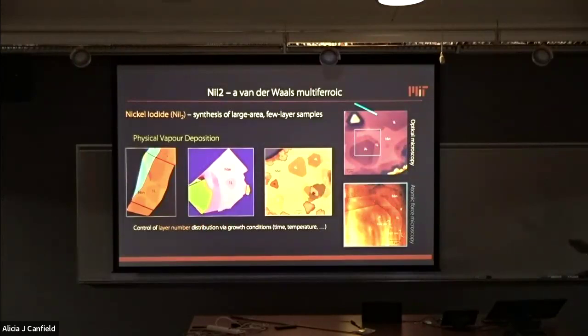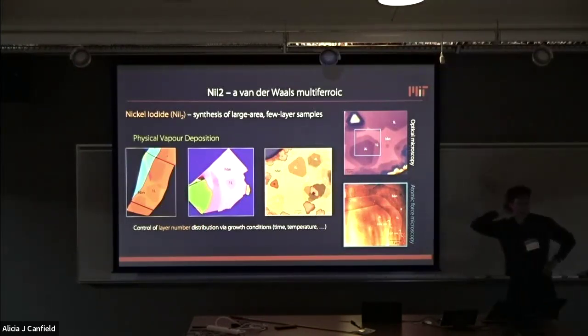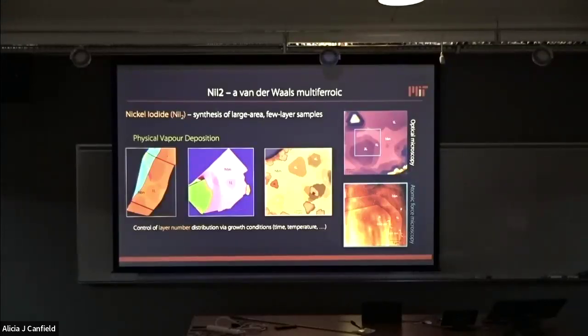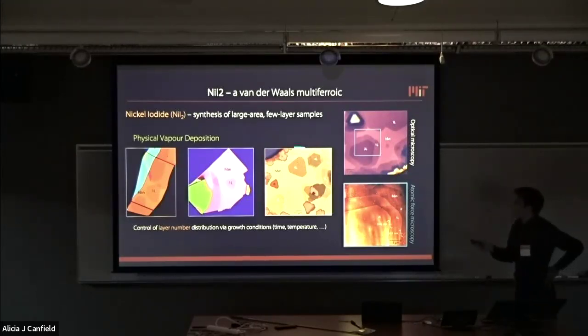So we went ahead and made the samples. These are some thin flakes that are grown in-house using physical vapor deposition in our lab. By tuning the growth conditions, we can go from samples that are mostly single layer to samples that have a distribution of different thicknesses, from 1 layer, 2 layer, 3 layer, which is great for the experiment that we do, because in the ultra-thin limit, we use optical probes to study the properties of the magnetic ground state. And having several samples at the same time of different thickness means that we can study the layer number dependence of the magnetic ground state all at the same time.